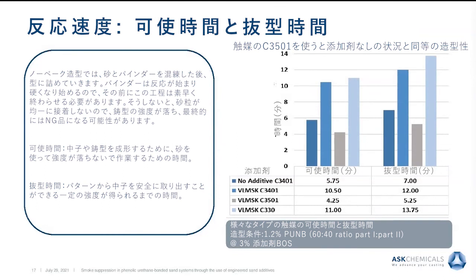So you don't want to get there. You want to try to work before that time and hand ram your sand or whatever you're doing. And then once you pass that time, now you have to watch for the strip time, which is the time where you have achieved certain strength so that you can safely remove your core or mold from the pattern. So on the right side, again, that's the same condition as I showed for tensile strength. For no additive, we're around 6 minutes.